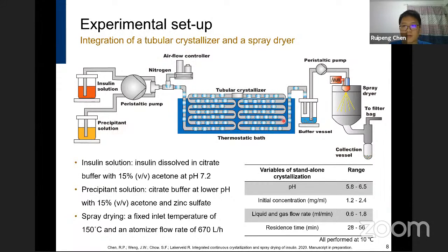And at the outlet of the crystallizer, we have a buffer vessel. For the standalone crystallization process, this can be used for sample taking and also to monitor the startup dynamics of the tubular crystallization. For the integrated process, the product slurry in the vessel is continuously transferred into the spray dryer using another peristaltic pump, which is operated at the same flow rate as the liquid flow rate in the tubular crystallizer. The spray drying was performed at fixed conditions, and this resulted in an outlet temperature for all conditions of around 85 degrees C, which is below the threshold of 120 degrees C.